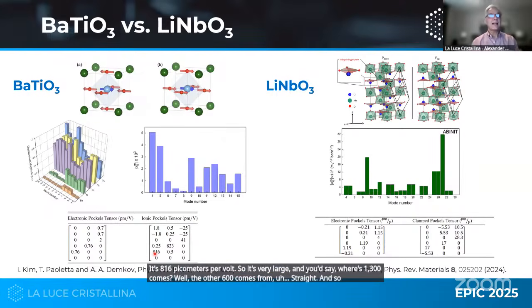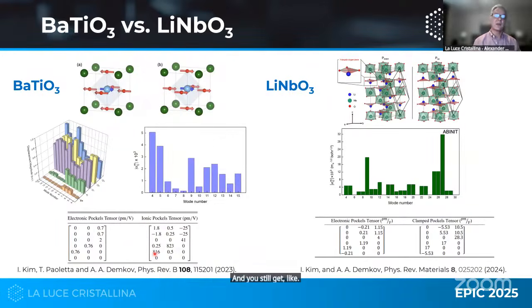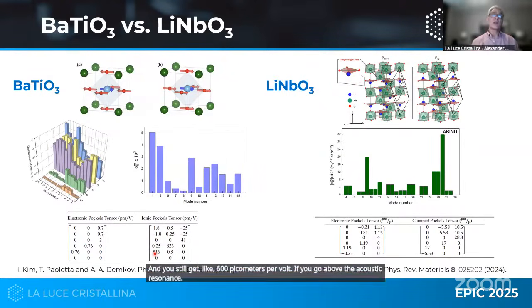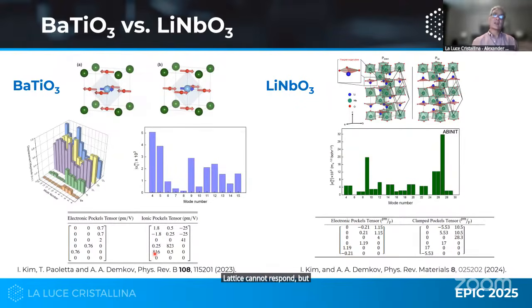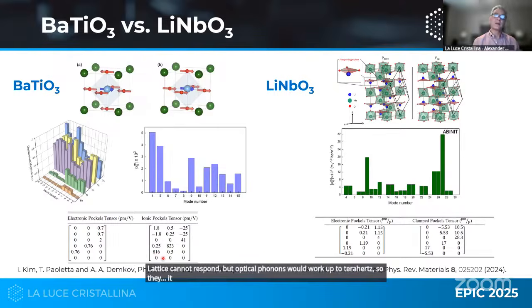And so that immediately tells you that barium titanate is versatile. At low frequency, optical phonons are depopulated, so you rely on strain, and you still get like 600 picometers per volt. If you go above the acoustic resonance, the lattice cannot respond, but optical phonons would work up to terahertz. So it would roll off, but it'll still be fairly high.